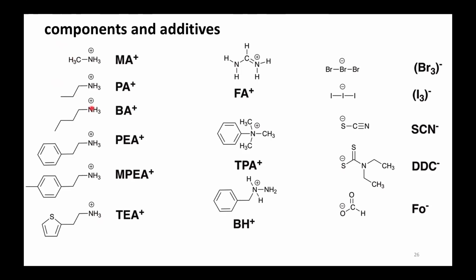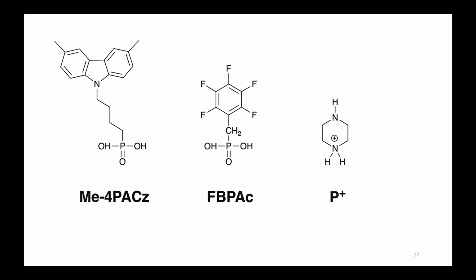Here we have some additives that do the reduction of the I2 to I-. And here we have some anionic additives, formates, the anion of formic acid, but also I3- and Br3-. They can take the place of the halogen, of the I-, and reduce the amount of defects. They interact better and they block the creation of defect states. So these are the typical chemicals that you can think about.